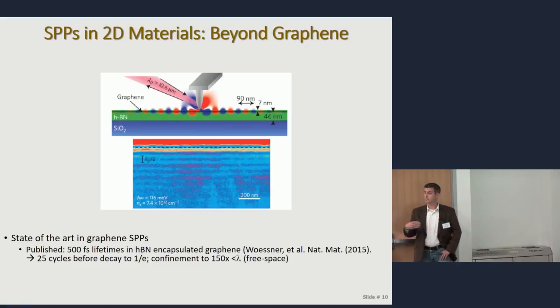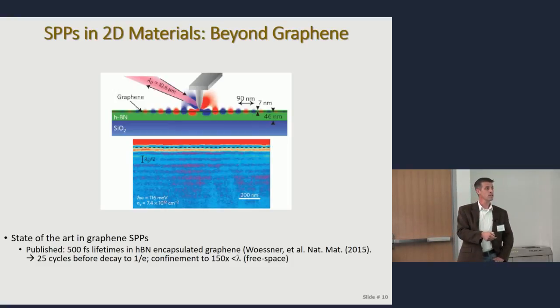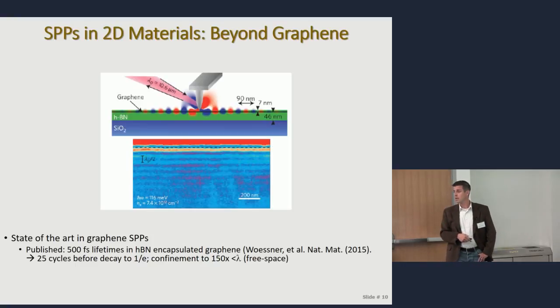All right? So this means a good deal of extension in the propagation length before it decays, while also maintaining this high confinement. Whereas usually, when I want a longer propagation length, I'm going to go to lower K, so I have a higher evanescent extent at the same time. So I'm losing confinement to get that longer propagation length, right? And you'll use things like metal-insulator-metal designs so you can compress that and kind of force the confinement of that light. Here you're doing it naturally just because you've reduced the scattering processes.